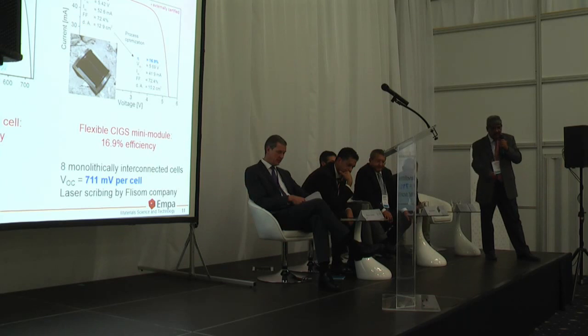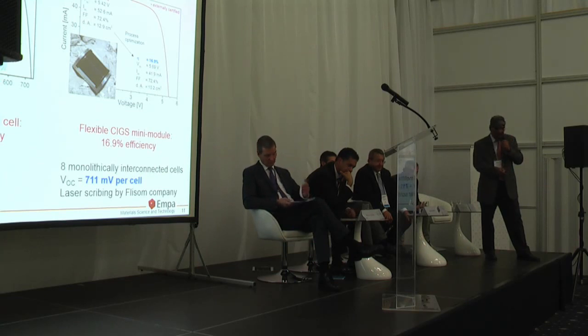So as I indicated to you in the beginning, the efficiency of 20.4% was achieved in the lab, which was the world record from our lab and which still holds. And this efficiency is quite high. But this efficiency is on a small area solar cell of 0.5 centimeter square. And then we had to make a monolithically interconnected module, and we were able to make, with the laser patterning, about 17% mini modules. So it showed that in principle the technology could be as efficient as multicrystalline silicon wafer technology in roll-to-roll manufacturing. And then you go on to the development phase, which takes many years.